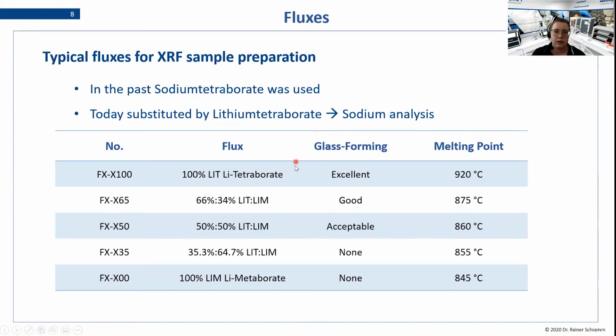So which kinds of fluxes are used then? We already talked about lithium tetraborate. You can see this here in my little table with typical fluxes as well. Then we have lithium metaborate down here. Lithium metaborate is actually not typically used in XRF sample preparation, but more for ICP. But what is used in XRF sample preparation is mixtures between both of them. So this is why I put it here as well. We have lithium tetraborate, lithium metaborate, and a lot of mixtures in between. We just put the most typical ones here in this table to not make it very large.